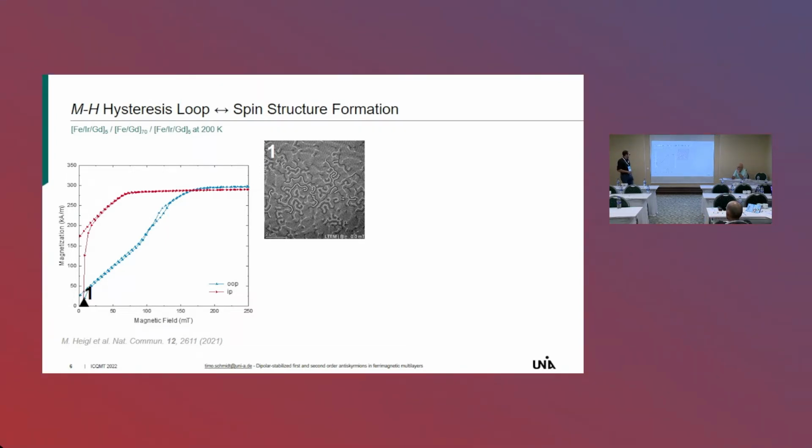And so this is that. Another thing you often see in Skyrmion samples is the small opening in the out-of-plane hysteresis loop, which comes from the fact that the nucleation and the annihilation of Skyrmions is an irreversible magnetization process.